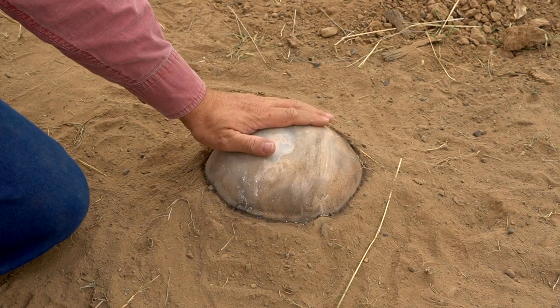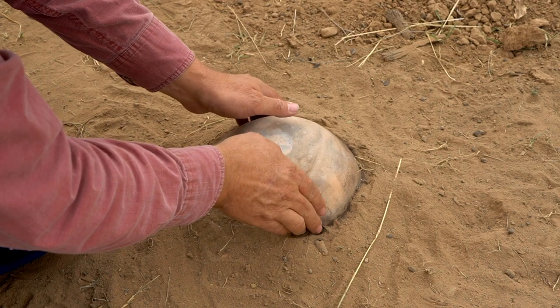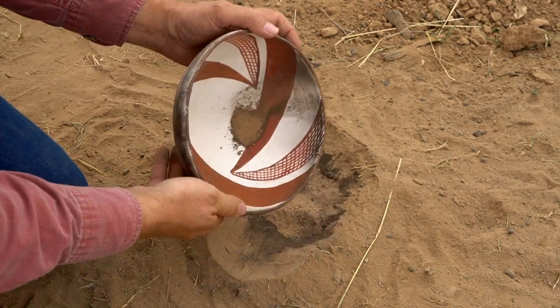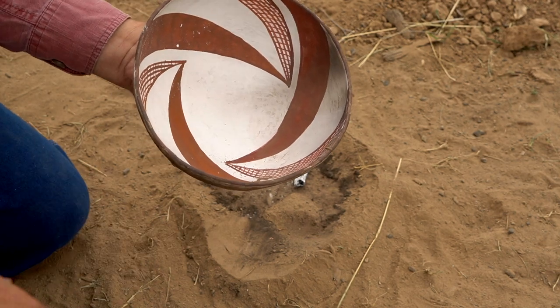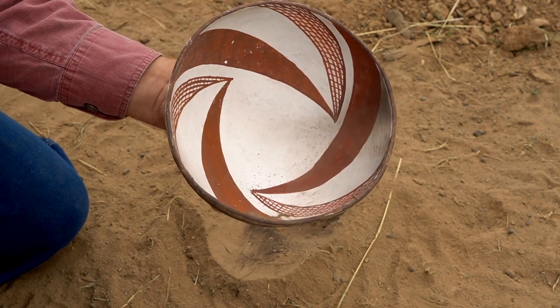Okay, this has cooled so that I can even touch it, so it's beyond oxidizing temperature. Let's see what it looks like. Oh my goodness — that is as red as red can be. In fact, it's significantly redder than it was before I fired it the second time. So the pull and smother is not working.